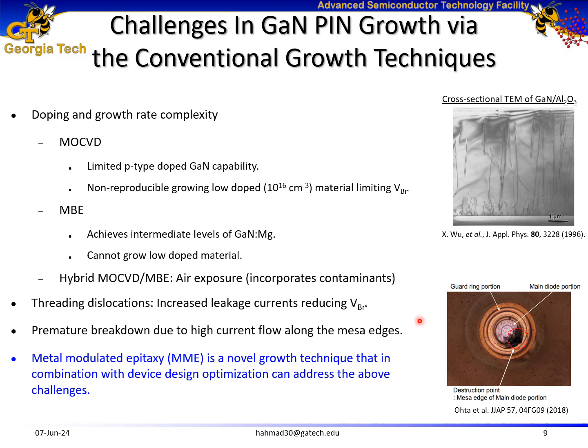Another issue in quasi-vertical pin diodes is threading dislocations, leading to increased leakage currents and reducing the breakdown performance of these devices. Also, from a fabrication point of view, it has been found that there is high current flow along the mesa edges, reducing the breakdown performance of these devices. Metal modulated epitaxy is a novel growth technique that, in combination with device design optimization, can address all these challenges.